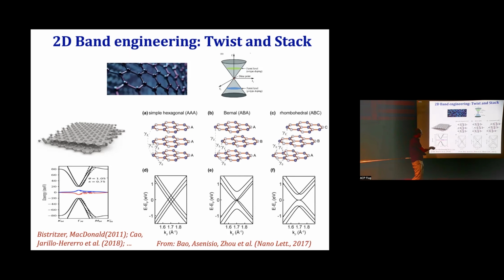you get that the electronic dispersion at low energy is linear. In the so-called Bernal or ABA stacking, it is quadratic at low energy. You actually have two bands: one is linear and the other one is quadratic. And in the ABC stacking, it's cubic. This is in a simple model, but it actually captures the actual dispersion pretty well. The cubic dispersion means that close to zero energy, the dispersion is very, very flat. The electrons are very slow. And if you tune the density of electrons just right, close to this point, the interaction effects will be very, very enhanced.